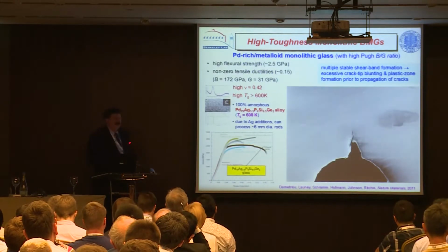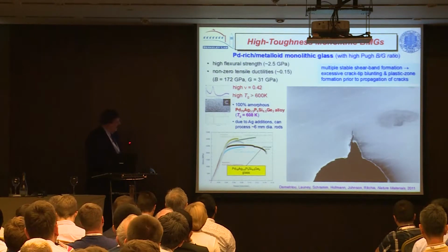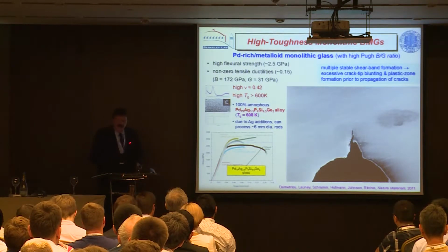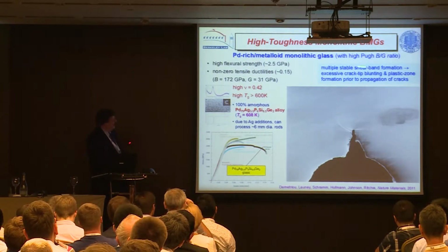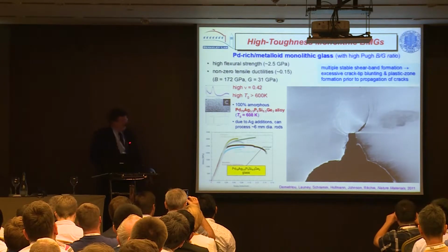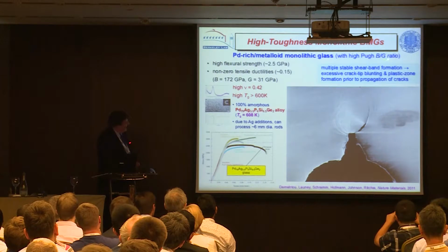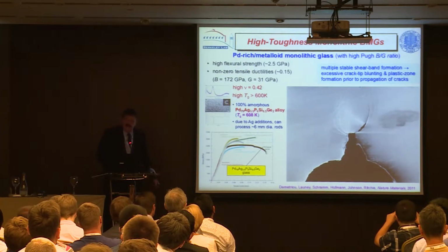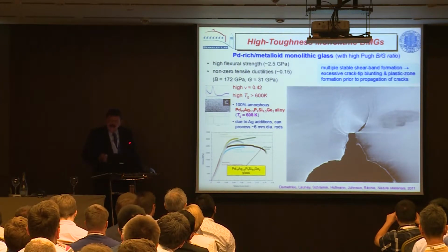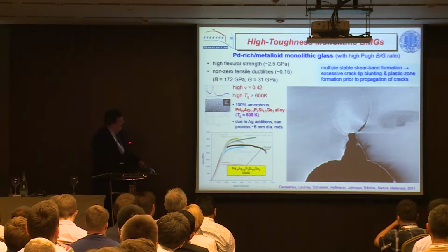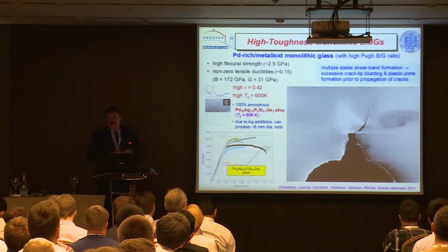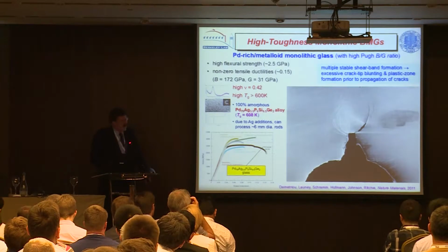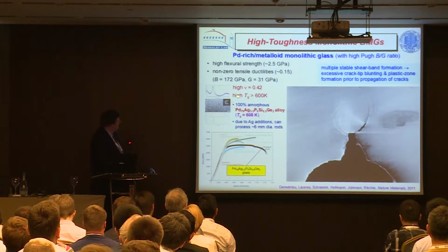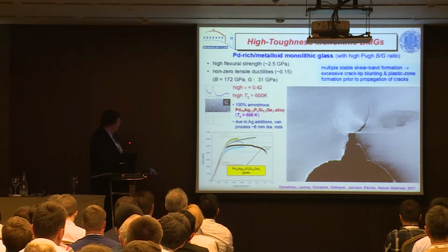We wondered if we could do this in a monolithic material too, and this is one of the toughest monolithic glasses. We went back to a very old, very hand-wavy notion, which is the Pugh ratio: if you had a high bulk to shear modulus ratio, low shear modulus would give you lots of shear bands, but a high bulk modulus would prevent them from opening up to form cracks, which is basically saying we want a high Poisson's ratio.